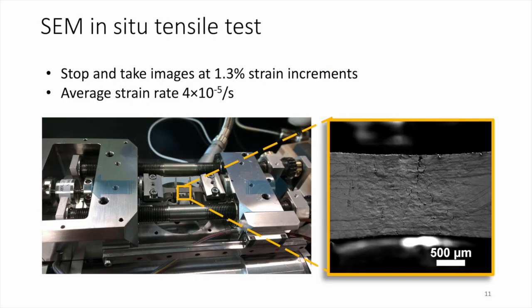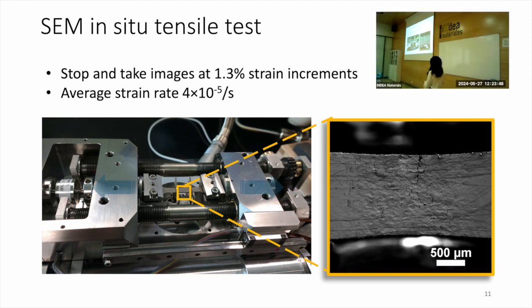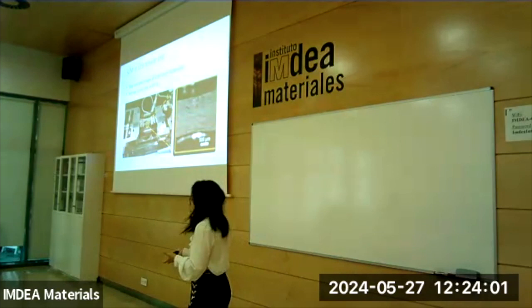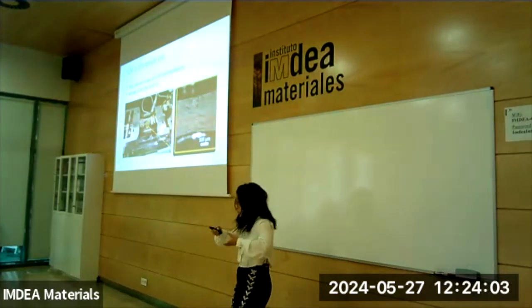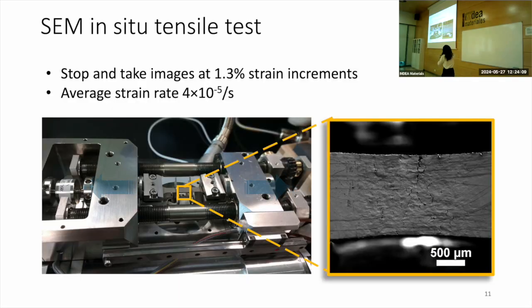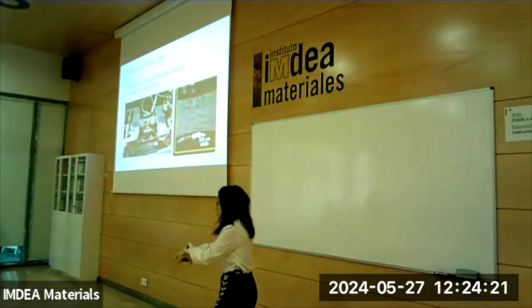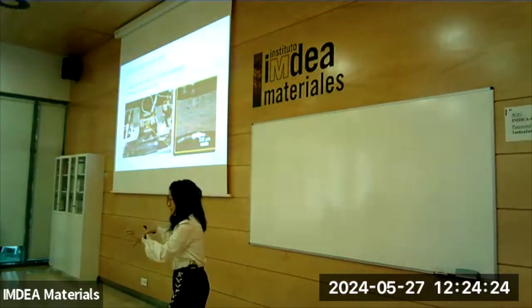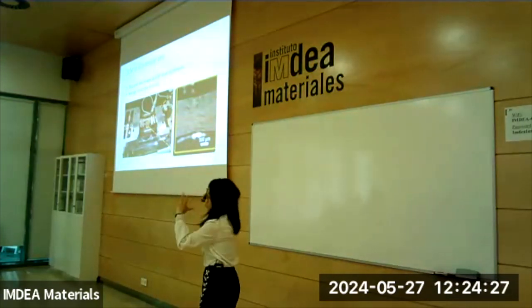Now we have different hydrogen charged samples. So we take these into the SEM and did in situ tensile test. We stop and take images at every 1.3% strain increment, and our average strain rate is 4 times 10 to the power of -5. For your information, when doing hydrogen embrittlement testing, hydrogen embrittlement happens at lower strain rate. The reason why we stop and take an image is, if you have experience with SEM, if your sample is shaking, then you won't be able to get a high resolution image. So we particularly stop there. We took a couple of images with high resolution and we stitched them together to get a bigger field.